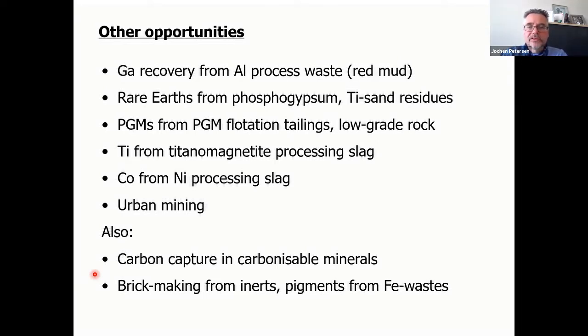So phosphogypsum, which is generated from the sulfuric acid leaching of apatite. The apatite is a classic collector for rare earth metals that then do not report to the solution, but stay in the solid phase and are then precipitated by the gypsum that forms as a product of the phosphogypsum process. And they're very difficult to recover from that.